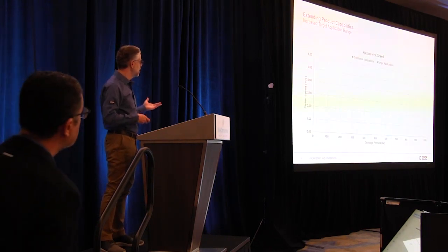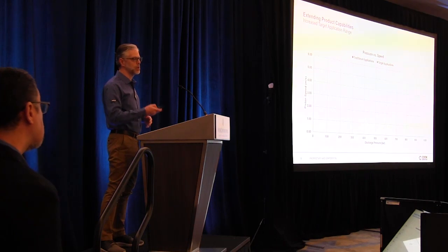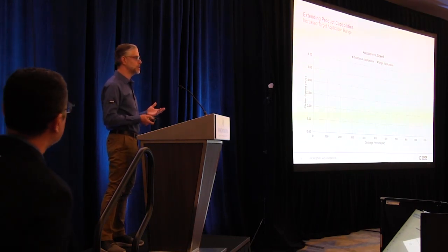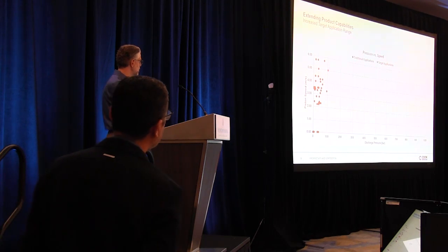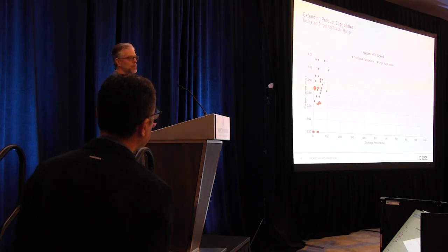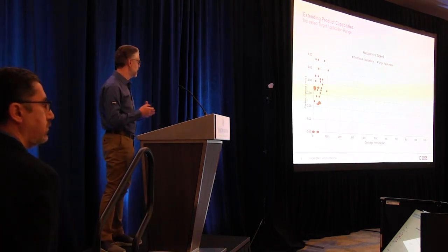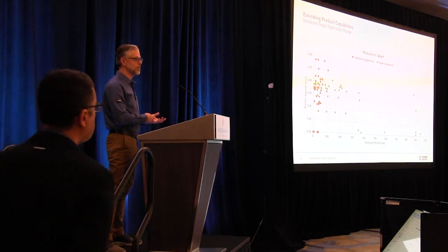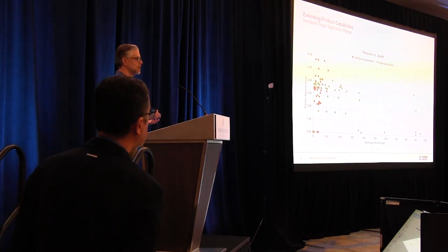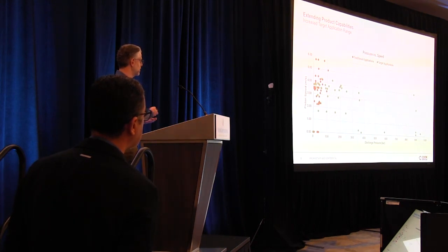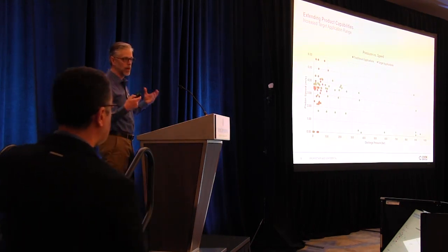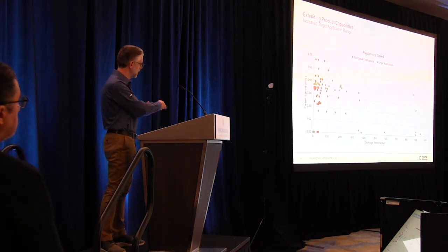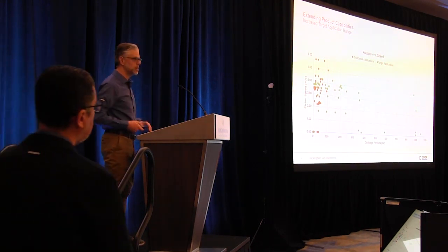So if we look at existing traditional applications for non-lube hydrogen and recip compressors, we're usually over in this range, right? We've got a range of sliding speeds here, but typically the limit on pressure there is about 100 bar in more common non-lube hydrogen applications, right? But now, this market is pushing the limits way out here. So we see quite a bit in the 300, 400, 500 bar range where we're looking at tank filling. But now, again, pushing all the way out here to 900 to 1,000 bar.